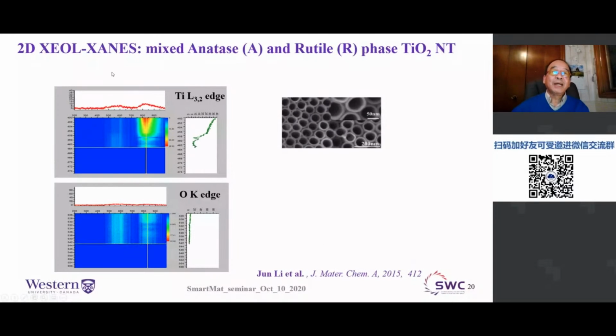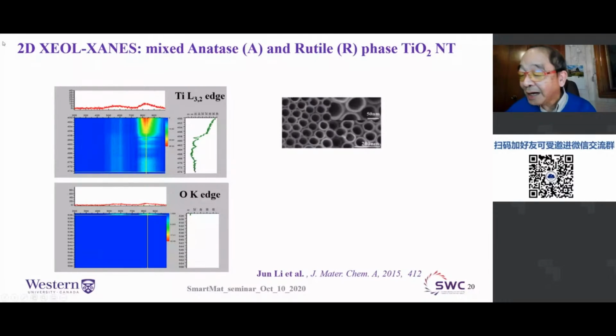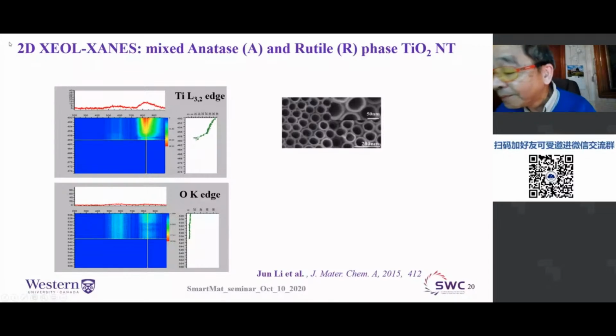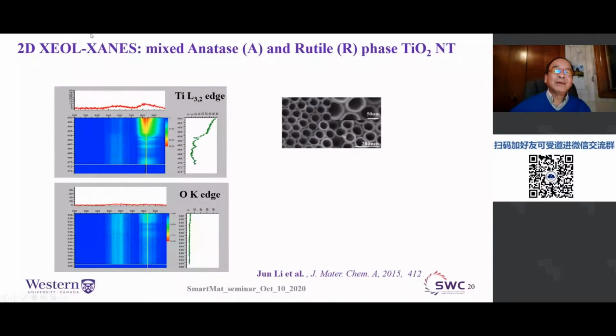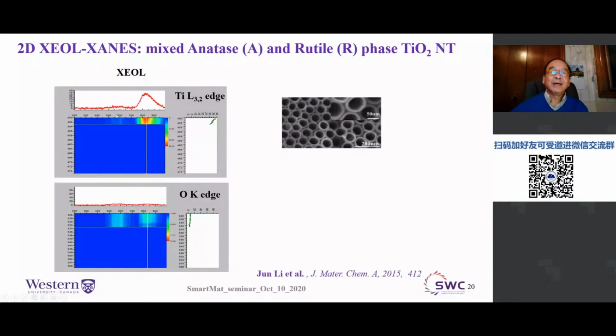Let me give you an example. We can do experiments in such a way that we can have both the XEOL, in this case of a mixed phase TiO2 nanotube, right? And this spectrum is the XEOL, and this is the XANES spectrum of the absorption.